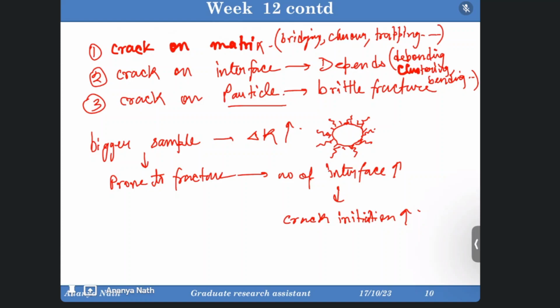So if we say this was the size of the particle x, and now this is the size of the particle which is y, 2y is equal to x. So the number of particles is more, so the crack initiation sites are more. So I'll add bigger particles? No, the bigger particles will lead to fracture. But if you are adding smaller particles, then the surface area which is embedded in the matrix is lesser. So there the chances of getting cracks and the crack initiation sites will be lesser than with bigger particles. So this concept is reversed. You'll understand more in the upcoming slides.